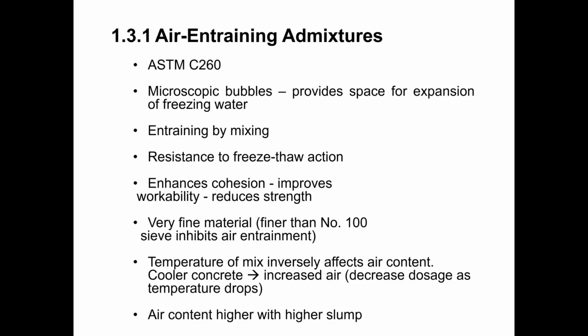All right, so the key reason we would use an air entraining admixture is to improve the performance of the concrete under freeze-thaw conditions, but there are also some other advantages to using air entraining admixtures. They enhance the cohesion of the components of the concrete, which improves the workability. So we can improve the workability without significantly reducing the strength, although we do see a strength reduction.